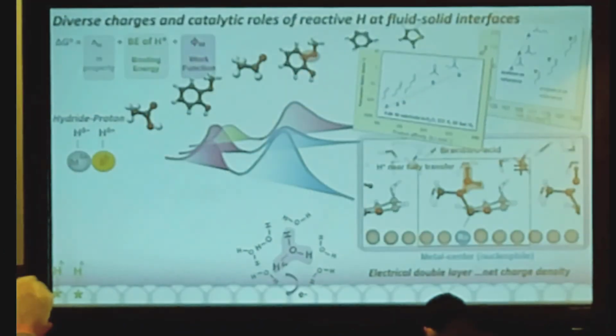And of course, this part here depends on the solvent identity, whether you have a polar protic solvent or a polar aprotic solvent, and that plays into this part of the chemistry, and that leads us to different reactivity tracks. Either the rate is increased by proton affinity for the aldehyde hydrogenation in the protic solvent, or the rate here is increased by hydride affinity for the aldehyde hydrogenation on the hydride proton pair.